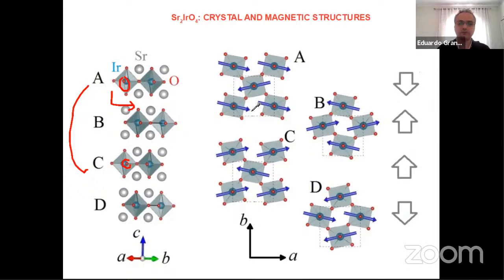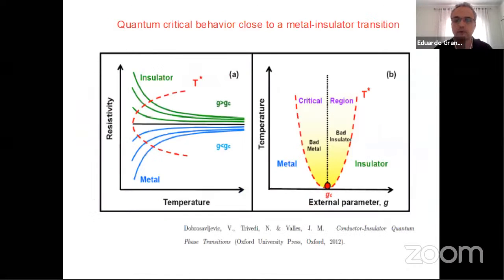So you can think of this magnetic structure like a compass, where the magnetic moment is guided by the orientation of the oxygen octahedra. So if the oxygen octahedron is rotated to one side, the magnetic moment goes to the same side, and for the other iridium octahedron, if it's rotated the other way, the moment also rotates the other way. And that's related to the very strong spin-orbit coupling, which leads to a very strong coupling between the orientation of the magnetic moments and the rotation of the octahedra.